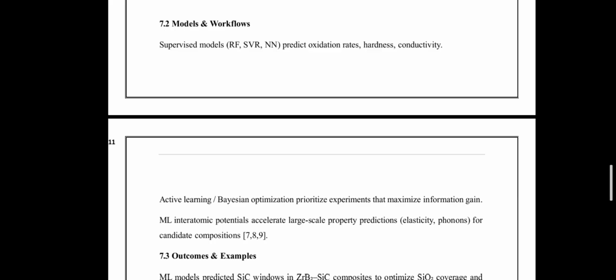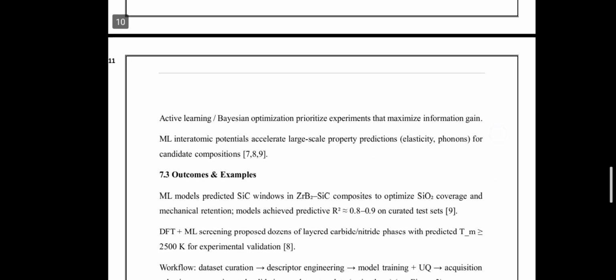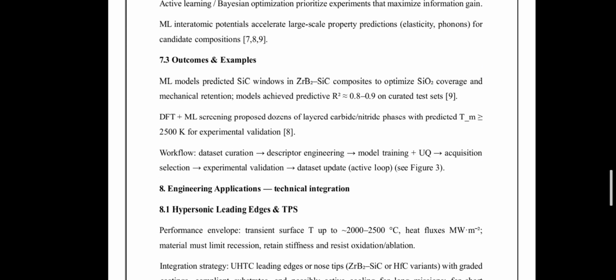So these are some workflows for our machine learning that we operate in our model to improve the design of the ultra high temperatures. Now we will see what their representative outcomes are. So, zirconium boride silicon carbide composites: the ML predicts the optimal silicon carbide fraction to form the protective silicon oxide glass scales while maintaining the mechanical strength, achieving an R2 of 0.8 to 0.9 on curated test sets.